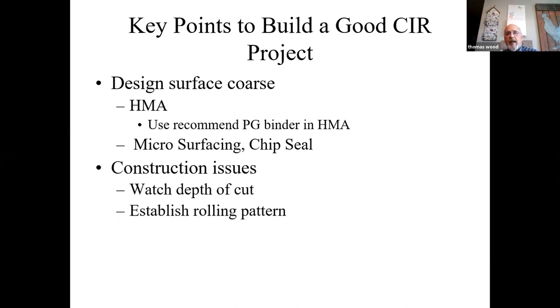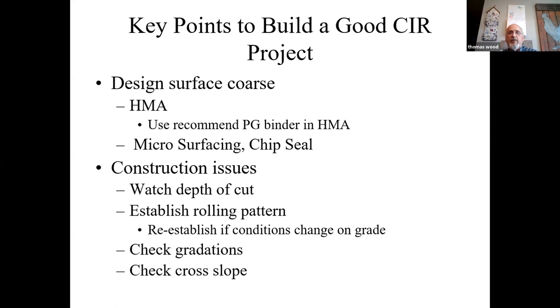Construction issues: watch the depth of cut, establish rolling pattern, re-establish rolling pattern. If there's changes on the grade, check gradations, check cross slope. They can, to a point, change the cross slope. If you've got a 1.5 and you want to make it a 2, they can help you toward that 2, but depending on how deep you're going, they probably can't get the full 2 because they've only got so much. They pave what they pick up.